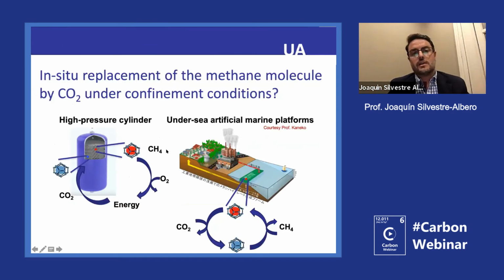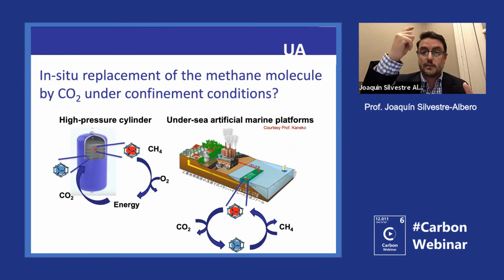And just to finish, the last experiment that we did in this research was to try to do the in-situ replacement of methane by CO2. Because at the beginning, I showed you that these cavities can allocate methane or they can also allocate other molecules. So the point is that if we are able to replace the molecules in situ, maybe we can use our natural hydrates to store large quantities of CO2 while taking the methane as a fuel.